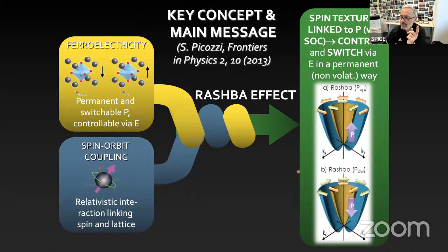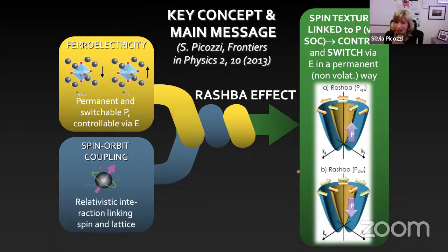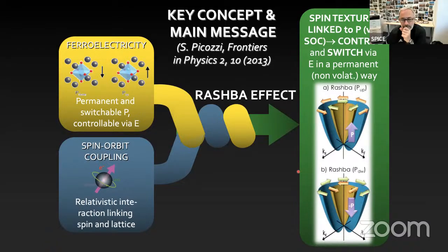I mean, also with the strain, actually, because I think you're referring to the Dresselhaus and the cubic components that won't have the polar, but with the strain, I believe you can have the polar one. But let's discuss that maybe in the Q&A. Okay. Dresselhaus, some people mean k cubed, but what I mean by Dresselhaus is something that has the breaking of inversion symmetry without having a polar axis, like the Zunger definition or something like this. But yeah, okay. In general, of course, any kind of spin-orbit coupling can produce a sort of spin splitting. But I believe for this effect you need a polar axis, right? It's not enough to break inversion symmetry, you need a polar axis. Exactly. But I think with some strain you can do that. Okay. Right. Yeah, sure.